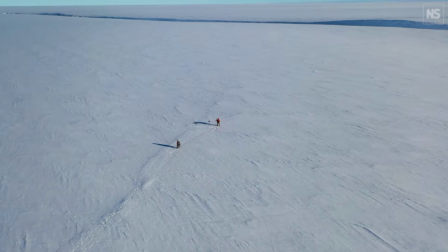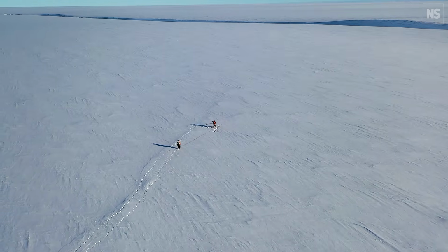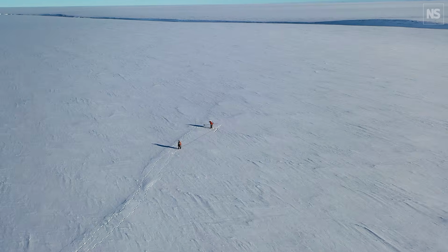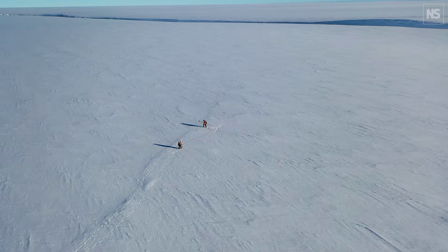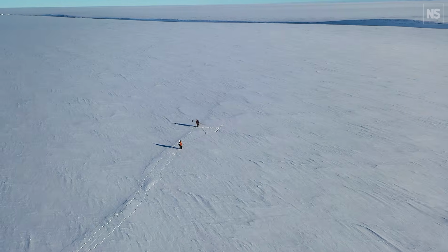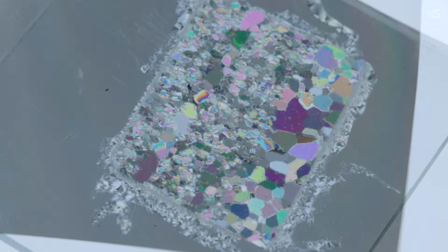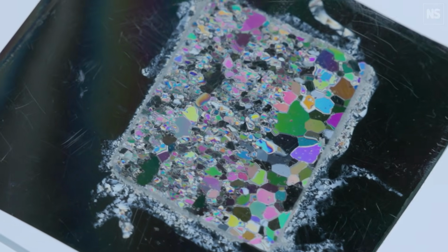We're actually finding that the weak firn snow is surprisingly stronger than previously thought. Lots of assumptions in the literature that this stuff is actually quite weak. We're actually seeing that the shallow snow is a lot stronger. In particular, we're finding these melt layers are much stronger. Nobody has measured the strength of these layers so far, to my knowledge.